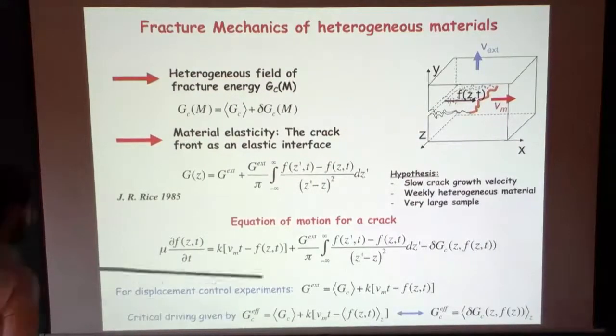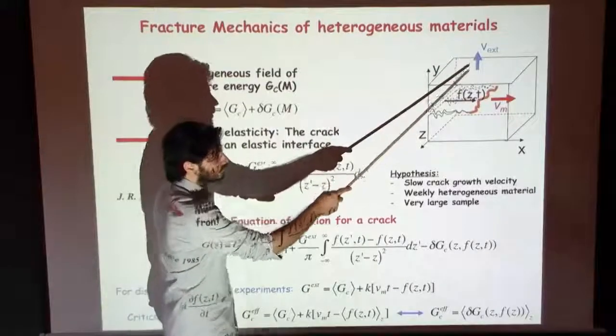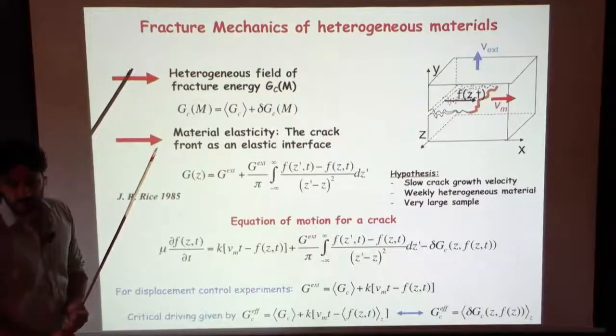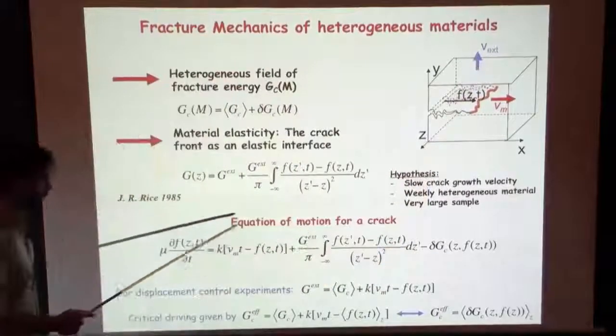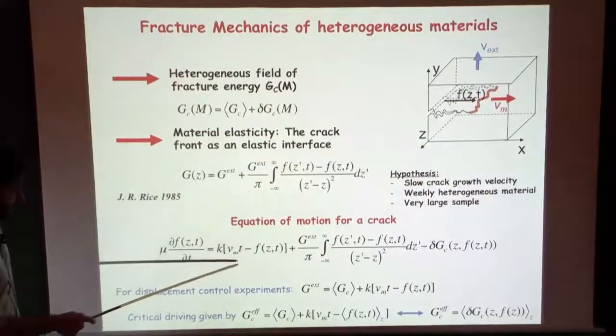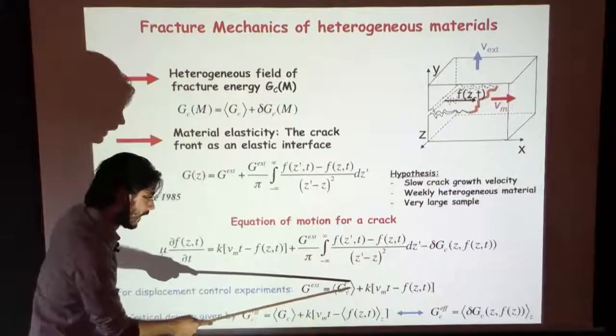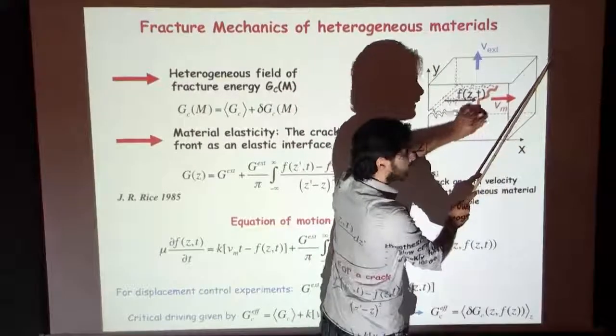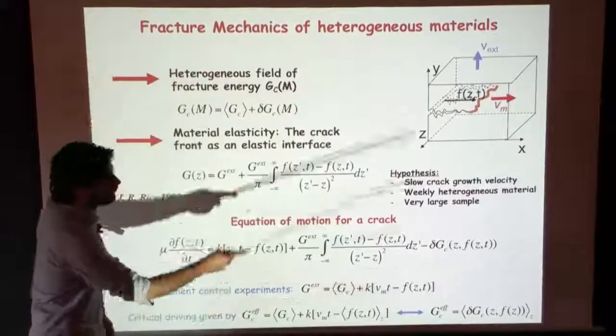In most experiments, we don't impose the load. We don't impose force or stress. We generally impose displacement. So that's not such a big difference. If you impose, for example, an opening velocity, you can show that the term that was there, G minus average GC, is going to simplify into this term. In other words, imposing a velocity here is going to impose a velocity of the front through a geometrical factor. Both are proportional, and you will have an effective driving that is a rigid bar moving at velocity Vm, the average crack velocity, pulling on your elastic line with some spring of constant k. And k we can calculate, and it depends on the geometry of your sample.